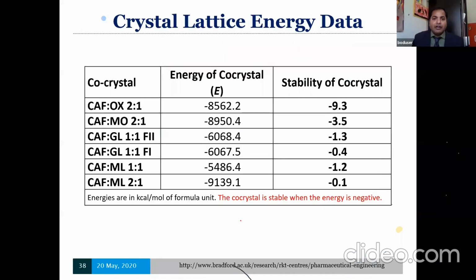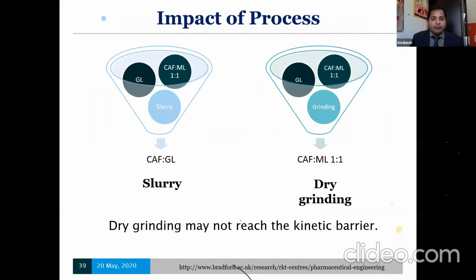We have also conducted some lattice energy calculations and saw what is happening with each of them. More negative energy represents the stability of the system. In the slurry conditions, what we figured out was the mixing is more efficient. During that point of time, you can expect more vulnerable things than with the dry grinding. So this is more prone to dissociation in slurry condition. This is where you want to test your formulation setup. So you have a co-crystal and you want to test under vigorous conditions at this stage. So we are taking the stable co-crystal system forward.